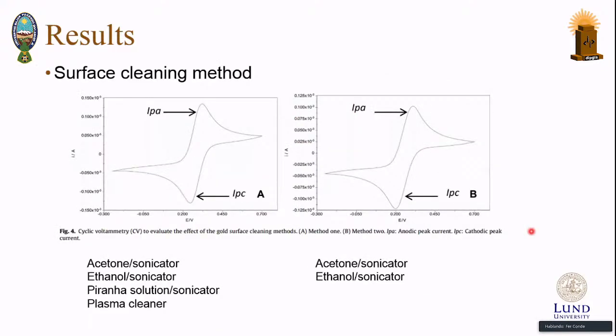As the main results, we developed a surface cleaning method, and we wanted to decrease the different solutions used and the steps, in order to have a cleaning method with fewer steps for all the detections. In the first part, we used the normal way to do the cleaning, which is acetone sonication, ethanol sonication, piranha solution, and then plasma cleaner. And in the second one, we used only acetone sonication and ethanol sonication, as these electrodes are new, so it is just necessary to use acetone and ethanol sonication.